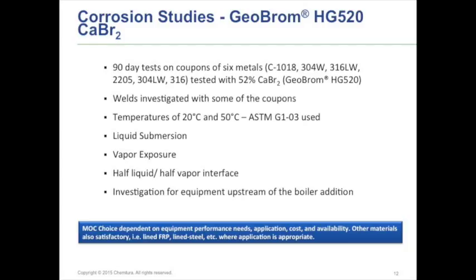At the boiler, really didn't see any problems there. You wouldn't really, at those temperatures, necessarily expect to. But where they did see a couple weld issues, it was analyzed that chloride was there, not bromine. So in that particular instance, they saw chloride present.